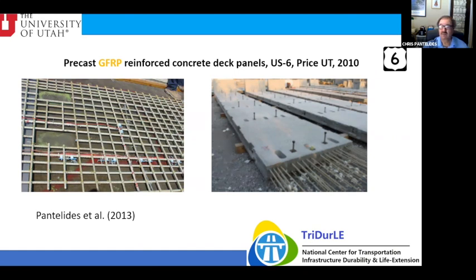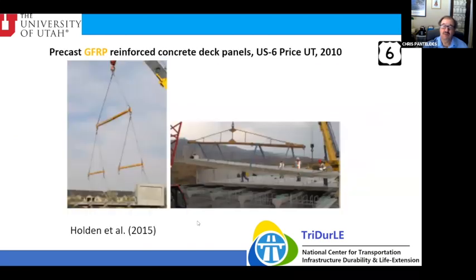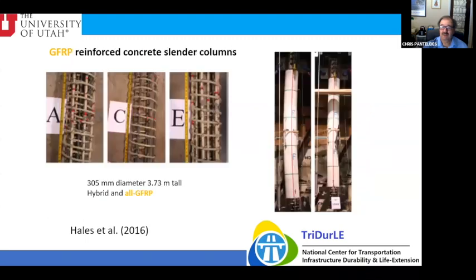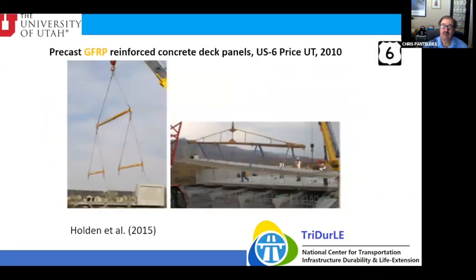These panels were then put on trucks and driven 130 miles to the site. You can see these panels being lifted where they were cast and being dropped on top of the bridge girders, just regular AASHTO type girders on this bridge on US 6. This bridge, by the way, has been in service now for 10 years with no sign of corrosion or any other degradation.